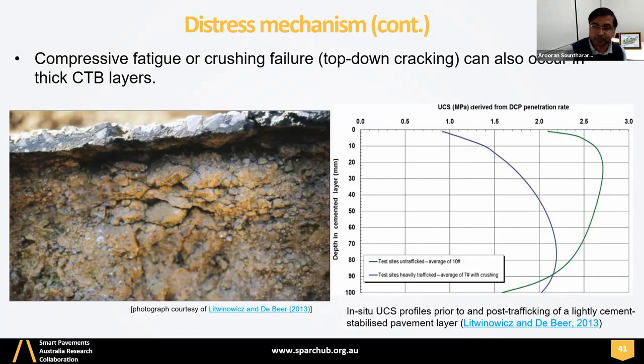If I use my pen here, closely look at this UCS value. This UCS value was generated using DCP, dynamic cone penetration test data. There's a direct correlation between DCP and UCS, which is unconfined compressive strength. Here you have the UCS value before trafficking, that means the as-built pavement, against the pavement depth. A 100 millimeter depth layer is captured, but the actual pavement depth is more than 100, and they have only captured that 100 part. The UCS has a small reduction at the start, then plateaus, and then decreases with depth.